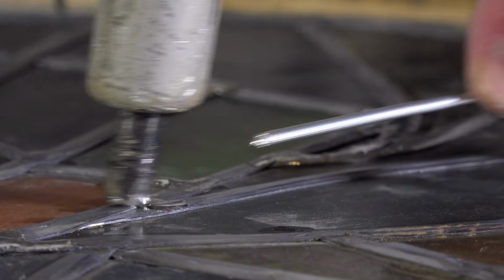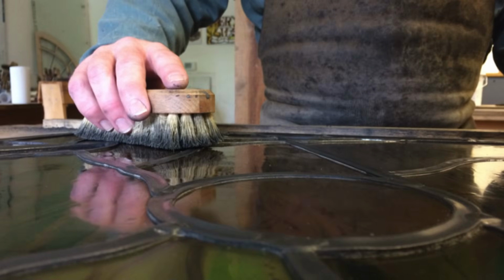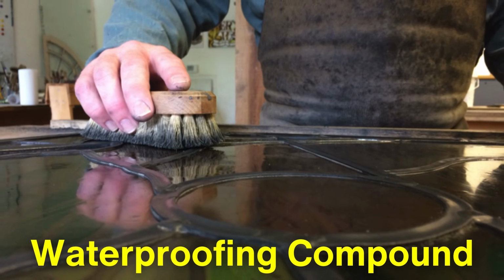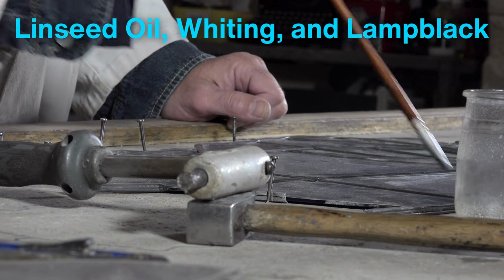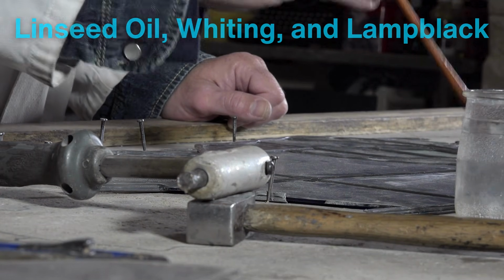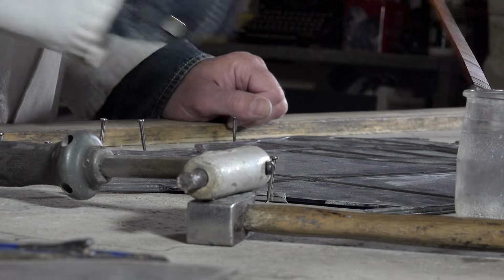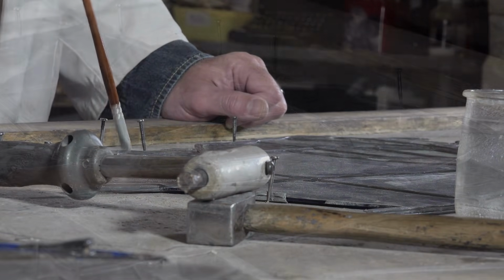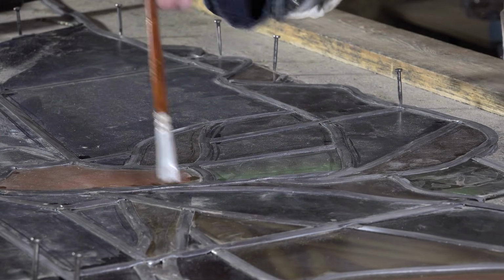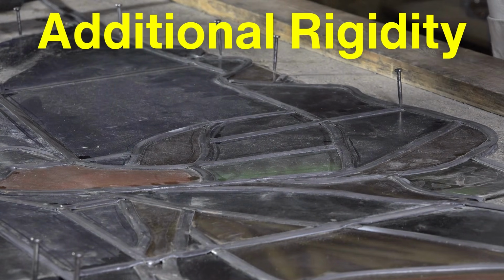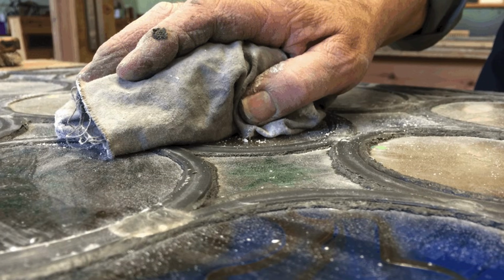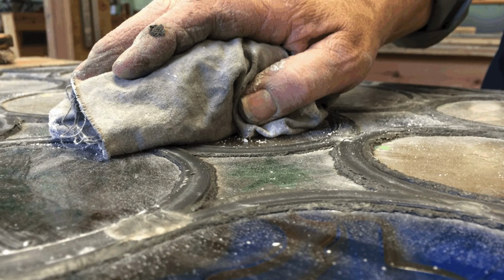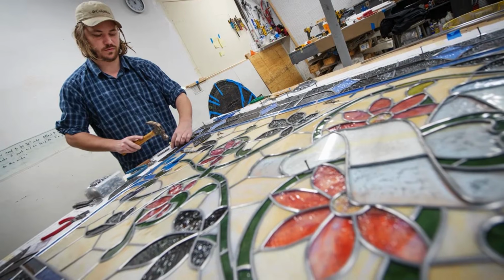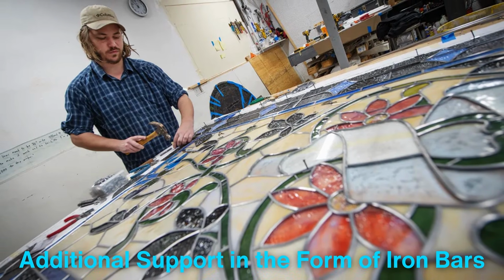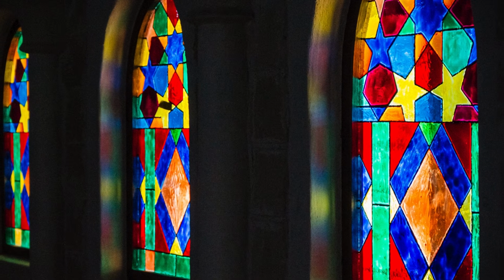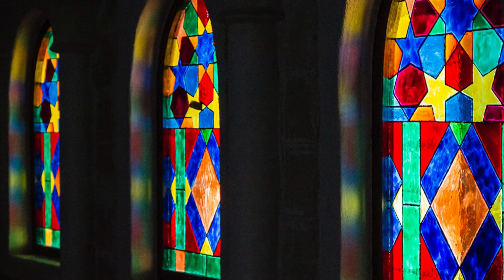Once the glass pieces were secured within the lead framework, the entire window was reinforced with a waterproofing compound. A mixture of linseed oil, whiting or chalk powder, and lamp black or a fine black pigment was brushed onto the surface of the lead and glass. This compound not only sealed the window against the elements, but also provided additional rigidity. The excess compound was cleaned off, leaving the window ready for installation. Larger windows required additional support in the form of iron bars, which were embedded into the masonry of the building to hold the weight of the glass securely.